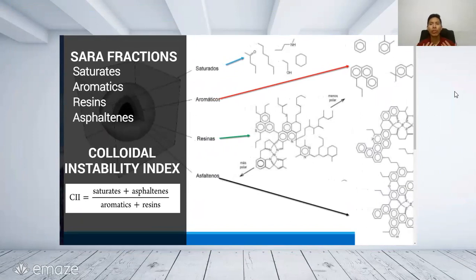And we know that the colloidal instability index is a method to determine the instability of an oil, which is based on the chemical composition of the crude oil, and it is calculated as the sum of saturates and asphaltenes divided by the sum of aromatics and resins. If the oil has a colloidal instability index value below 0.7, it is defined as stable. And if the colloidal instability index is higher than 0.9, it is considered unstable.